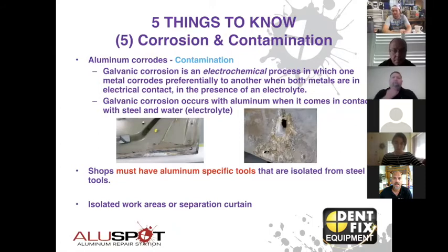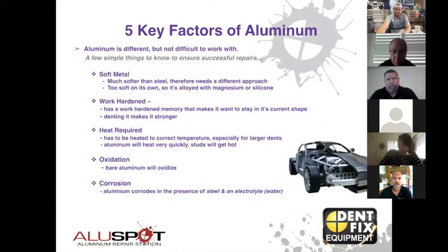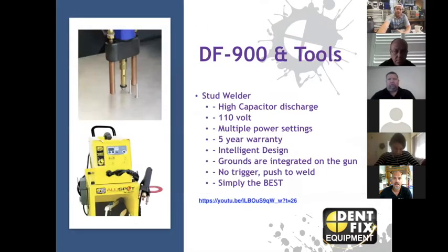So we talked about corrosion and contamination. Aluminum will start to corrode in the presence of a more noble metal and an electrolyte like water, you know, moisture. And so what happens is that corrosion will really want to attack the less noble metal like aluminum. That's why we don't want to intermix our steel tools with our aluminum tools. It's really important to keep them separate. So again, back to that initial thing: it's soft, work hardened, heat required, oxidation, corrosion. Hopefully that makes sense on a couple of the key factors that you want to know to ensure successful repairs.